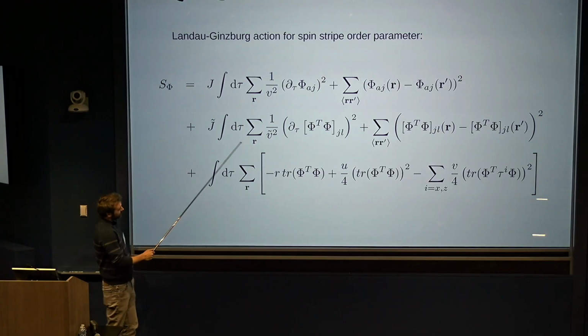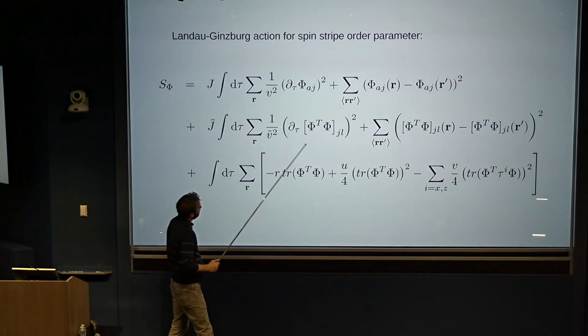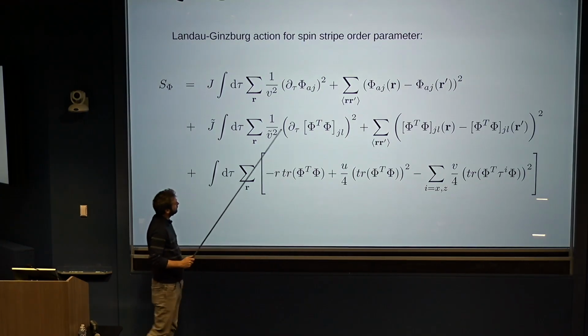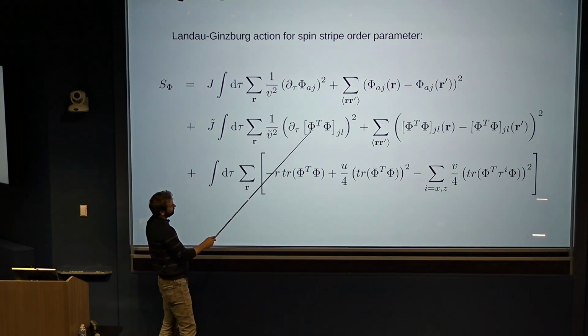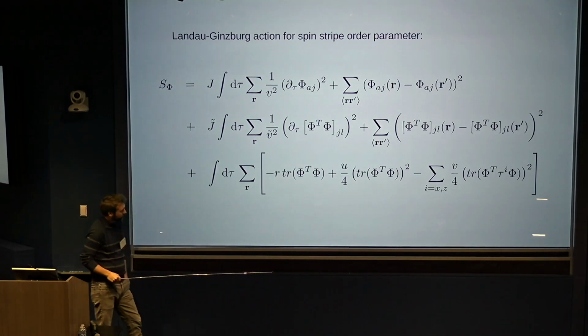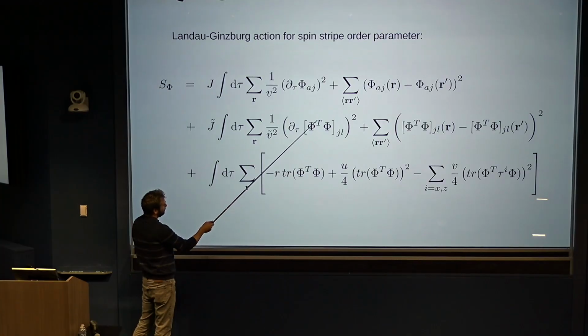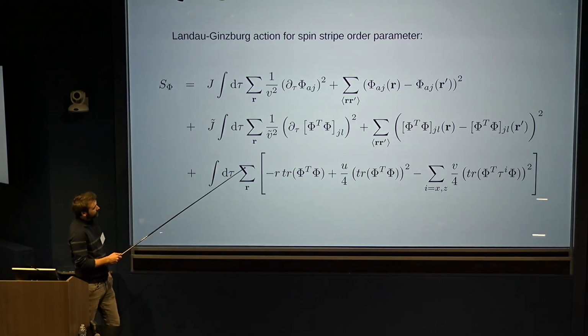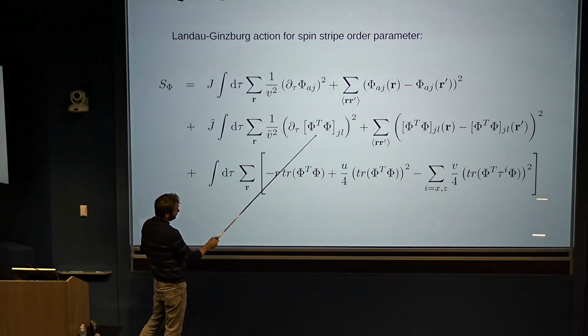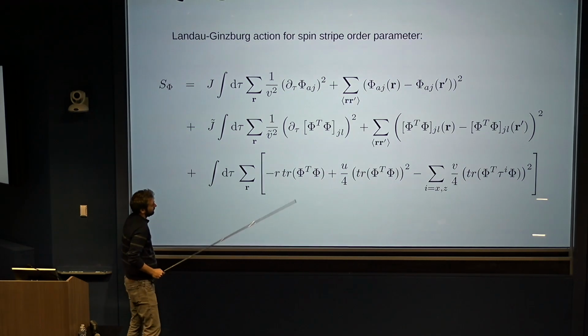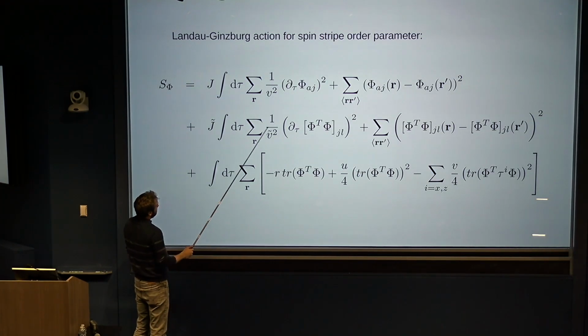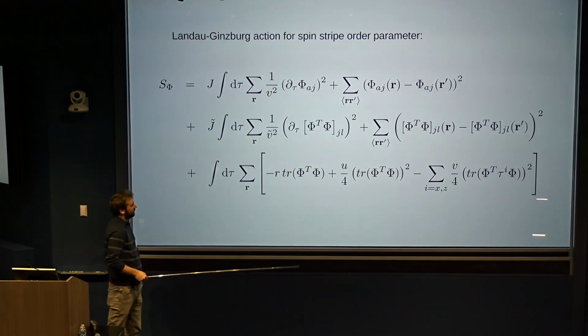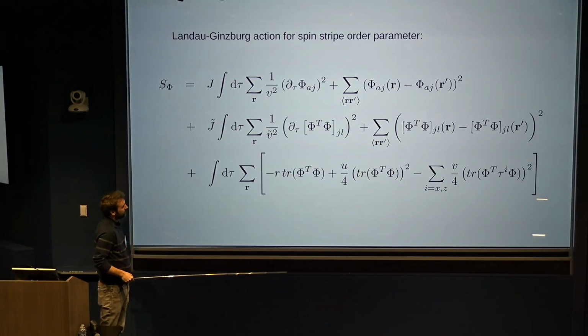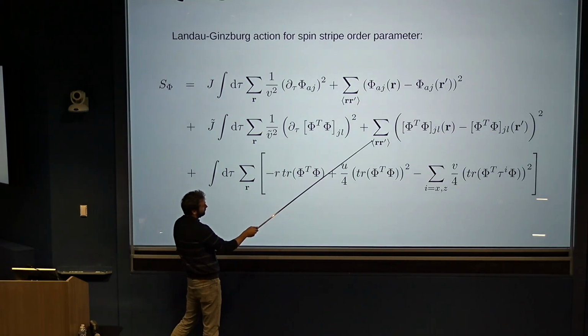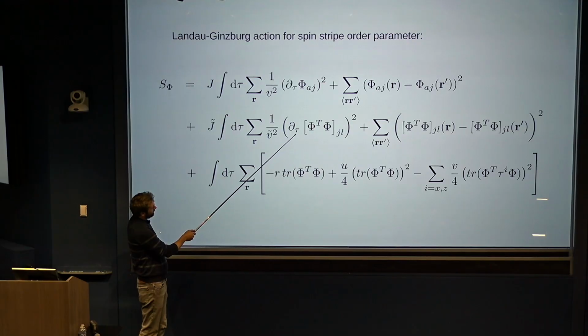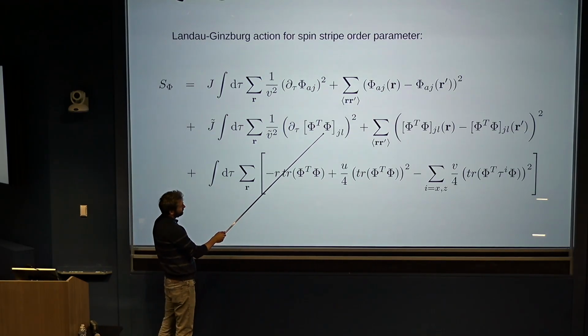And then what remains is the middle line here, these two terms. They're again temporal and spatial stiffness terms, but now not for phi, not for our original field, but for this composite field phi times phi transpose. This composite field also goes under the name of a vestigial order parameter. It's an order parameter for vestigial order. And basically these two terms are insensitive to the phason fluctuations of your charge density wave order. So they're insensitive to charge fluctuations, but they raise the action. They are sensitive to fluctuations in the spins.